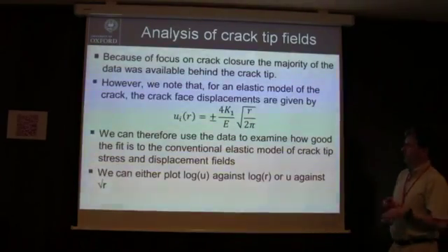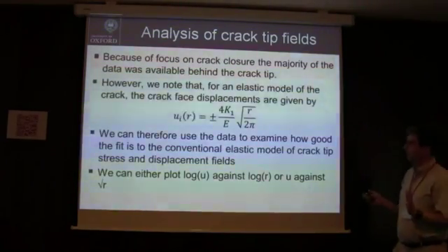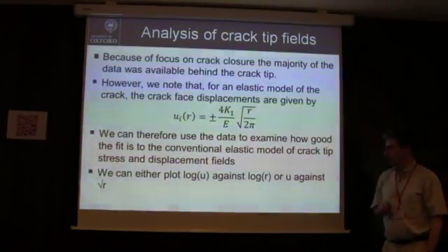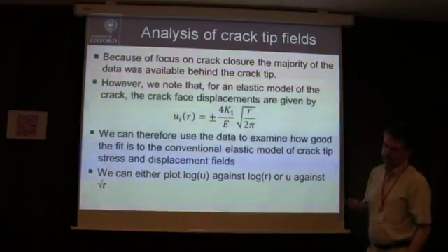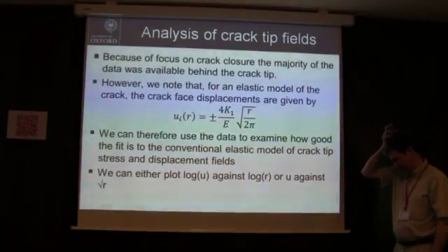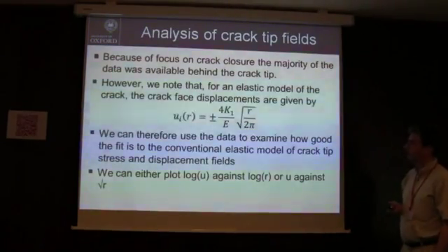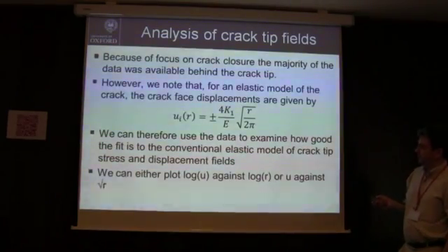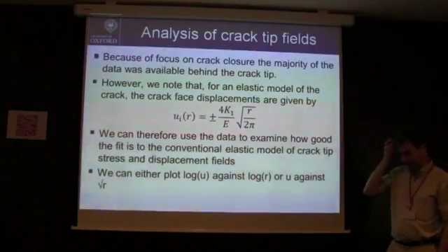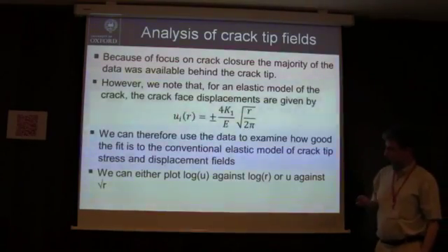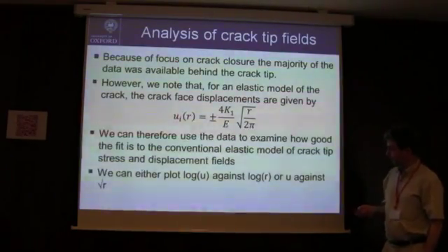Now, okay, that's fine, and you can go on and do an analysis of closure. But that wasn't what we wanted to do here. When the Forni di Sopra workshop came along, we thought, what on earth can we present that's got relevance to crack tip stress fields, as opposed to what's happening down behind the crack? Well, what you can do, of course, is take the straightforward elastic solution for displacements, which gives the relative displacement across the crack as a function of position from the crack tip.